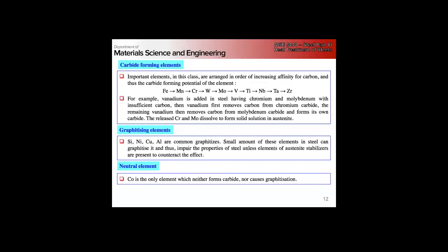Not well. Because we've seen in some occasions where even when you do have titanium, it preferentially forms chromium carbides. That's interesting. So this is basically just energetics of formation, right? This is the enthalpy of formation is how these are ranked. There's no kinetics necessarily taken into account here.